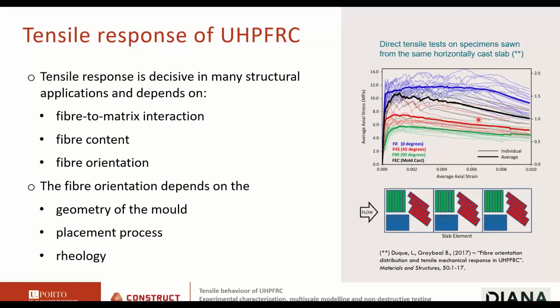And the most striking thing is that if you cast the test specimen individually in a dedicated formwork, you get a different behavior, which is represented here with a black curve, from what you get in the structure. So this is a very particular aspect of this material.